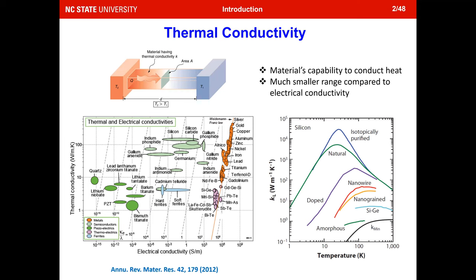Compared to electrical conductivity, as you can see from the left figure, which spans about 24 orders of magnitude, thermal conductivity only spans 5 orders of magnitude. So if you have thermal conductivity around 0.1 watt per meter per Kelvin, it's already a pretty good thermal insulator. And if you have a thermal conductivity around 1000 watt per meter per Kelvin, it's a good thermal conductor. So we don't really have a large range to work with in engineering materials.